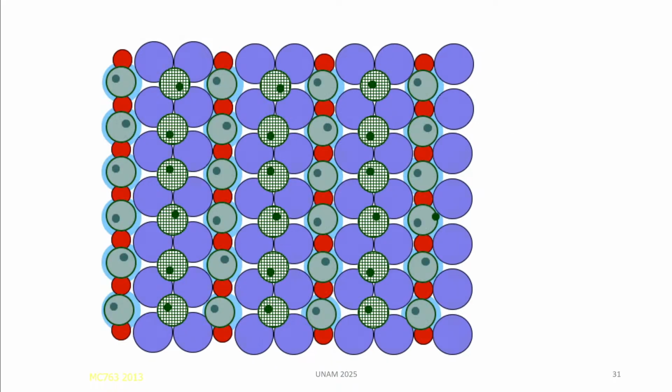And this is the resulting state. You see this water has lost one H+, and given it to the O2-, you are left with 2 OH- hydroxide ions, but they are not in the same surrounding. This one is terminal on a single Ti4+ ion, and these are bridging between 2 Ti4+ ions.